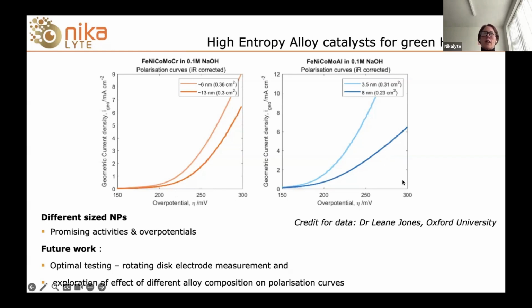And it's not clear whether that's down to an effect of the surface area, because in both cases we have the same density of material, the same loading. Not really sure why that's the case, but it's very interesting to see that effect. We also see that the overpotentials in both cases are quite promising, and of the order of what we were hoping to see for an OER catalyst.